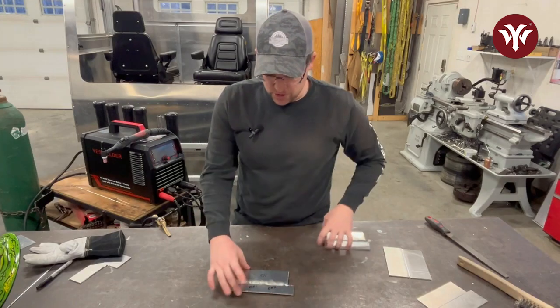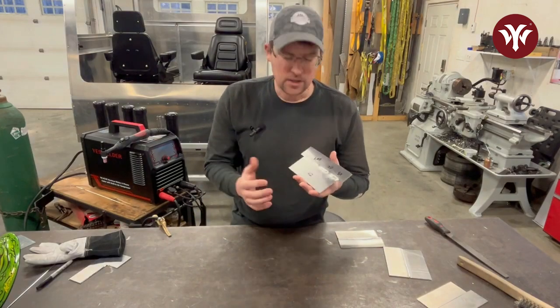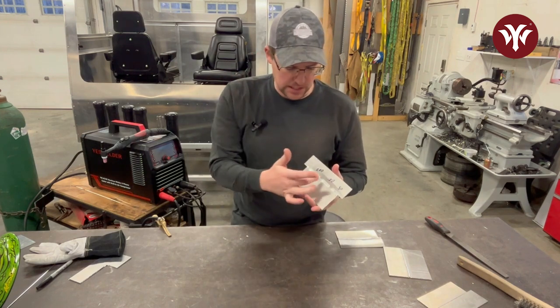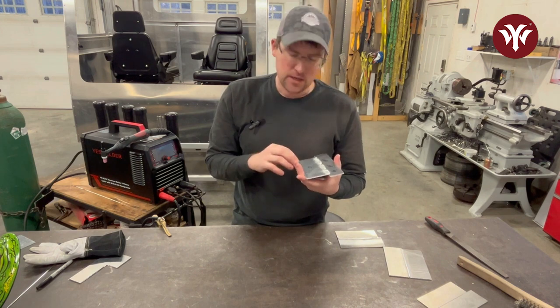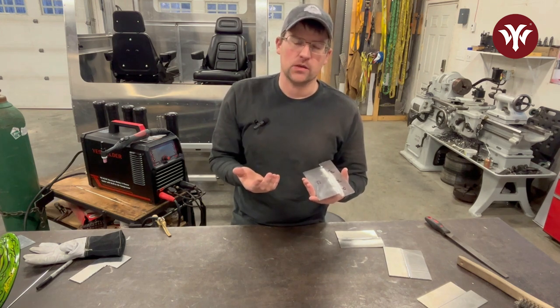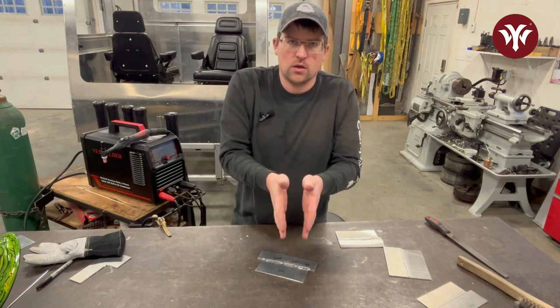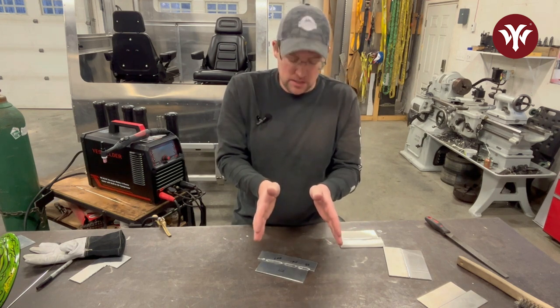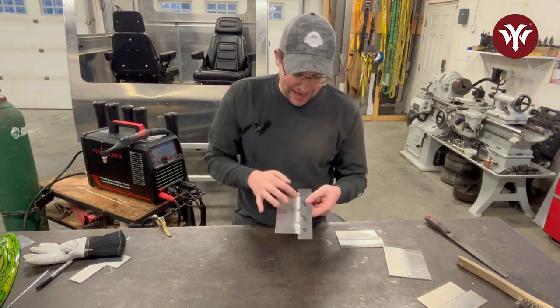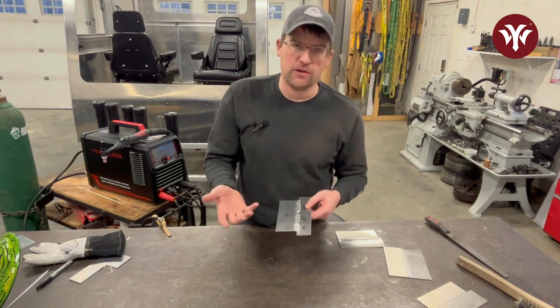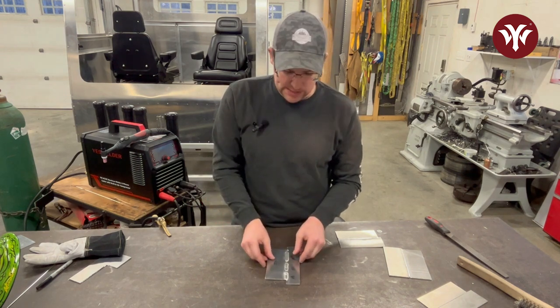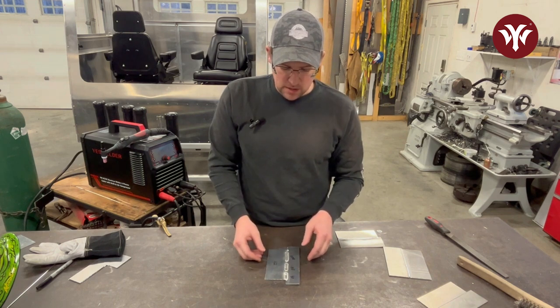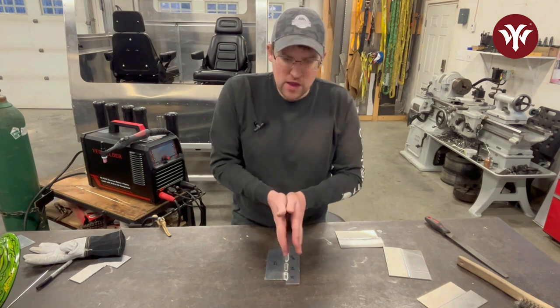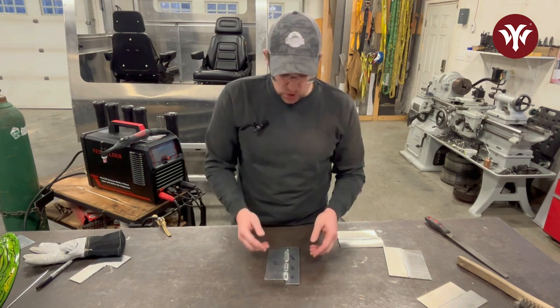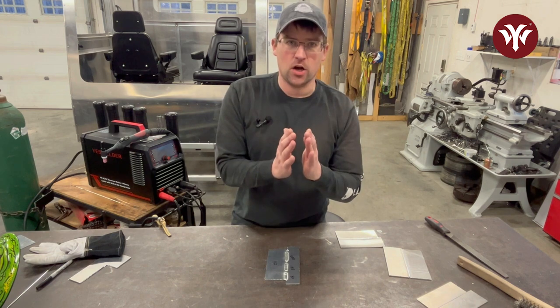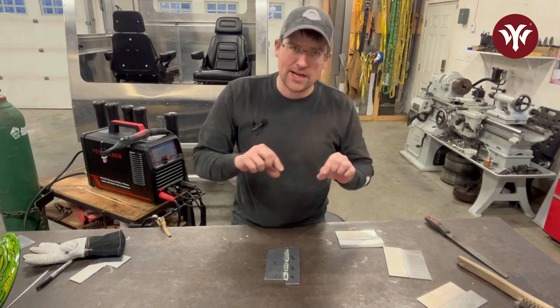All right, well, I showed you what changing the frequency did there. Really, you could hear the difference between 50, 100, and 200 hertz. If you do any research on adjusting the frequency when AC TIG welding, it really has to do with adjusting your arc and the width of your puddle and everything like that. I didn't see a ton of that happen here, but that is what frequency adjustment is for. A lower frequency like 50 hertz is going to create more heat into your part. The arc widens out. And as you go to higher frequencies, it's gonna really tighten that arc up, bring it much into a tighter bead.